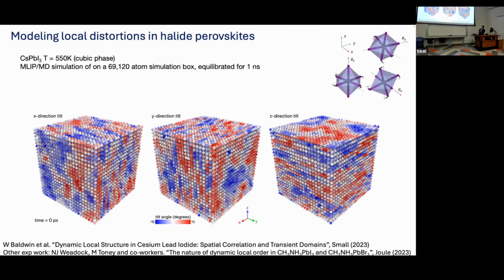So what you see are these pockets of blue and red, meaning octahedral tilting dynamically in one direction versus the other. And occasionally in the simulation, you'll see these sort of staggered faults, where one axis of the unit cell in the simulation box shows that it's tilting in one direction, and to accommodate that, the next layer will tilt in the other direction. So the structure is not something like we typically view, like simple cubic, but it's actually quite dynamic. So this is the simulation for 550 Kelvin.